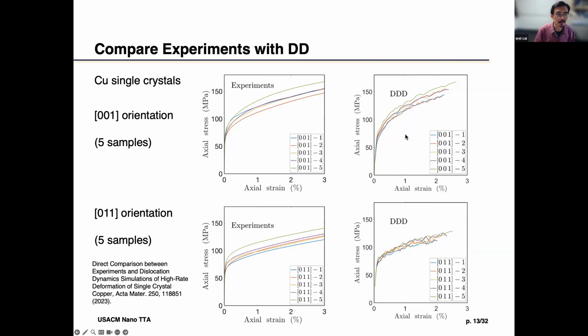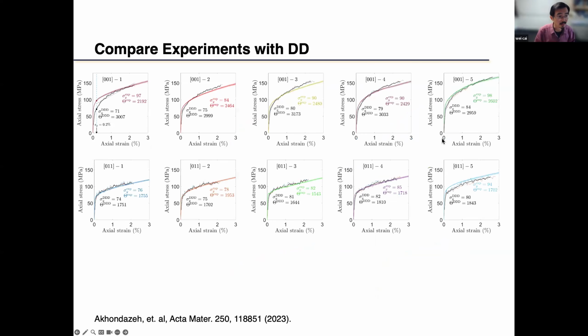So these are the experiments and simulations for the 10 samples on top of each other, right? Let's see, I always try to figure out which ones. I think the experiment is the smooth colored curve, and then the DD simulation, because we repeat it multiple times, is the more zigzag curve. And you can see that it has a fairly good agreement. So we were quite encouraged by that.